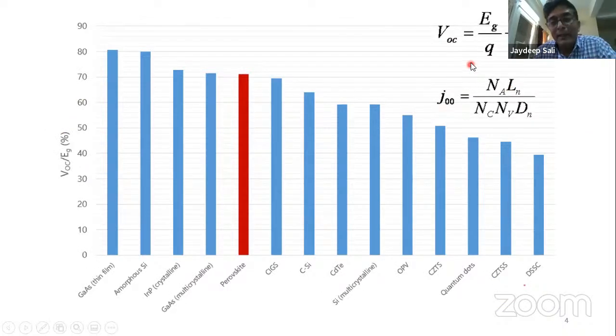Okay, so ideally the ratio should be 1, but as you can see, there are different losses, recombination losses present in the optical devices, and that makes this ratio much less than 1. So having this VOC by EG ratio, expressed in percent, as high as possible is an indication of a good candidate for solar cell technology. So here lies the perovskite material. You can see it is having a VOC by EG ratio of more than 70%, indicating much less optical losses in this material.